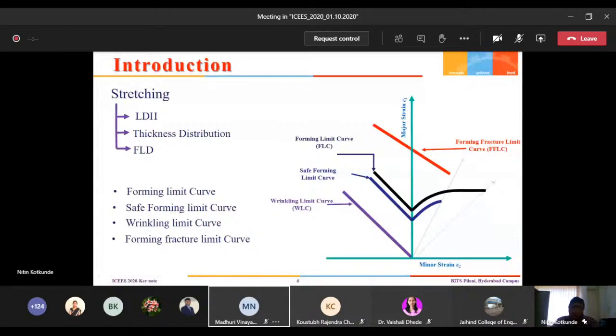In some cases, especially when we do incremental forming or metal spinning, you will not get this traditional FLC curve. We have a forming fracture limit diagram, because all the fractures happen in plane strain condition, so you will get a straight line. This is especially so for high strength materials where ductility is limited and there is no substantial necking tendency. For example, with Inconel alloys and titanium alloys, such high strength alloys, you will never get the traditional FLC like the other materials.